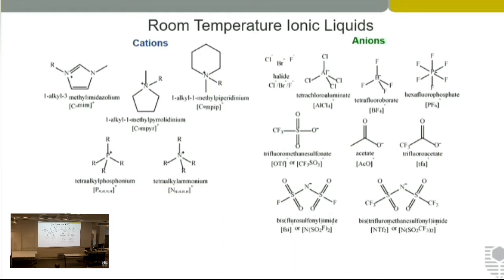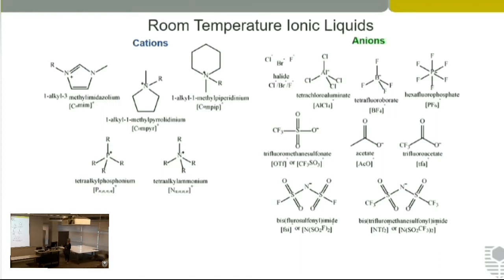The ones we usually use for our electrochemical experiments are often based on imidazolium cations or pyrrolidinium, piperidinium, and these longer chained tetraalkyl phosphoniums and ammoniums. Each cation is paired with an anion. The ones which would technically be ionic liquids, but not room temperature ionic liquids, would have some halides. But as you get to larger structures, such as this FSI or the NTF2, you can have very liquid ionic liquids at room temperature.